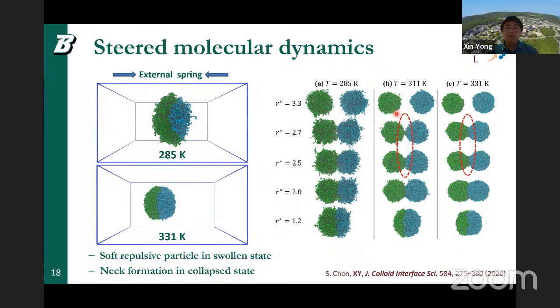So the interesting observation we see here is that at low temperature, when these microgels are swollen and fluffy, they show basically pure repulsion. As you can see here, when they come close, they deform, and they really don't like to interact with each other. On the other hand, when temperature increases, we start to observe a very characteristic neck formation or bridge formation, which is reminiscent of droplet coalescence. That indicates these particles are very adhesive to each other, and the surface tensions start to play a role, which allows them to spontaneously interact.